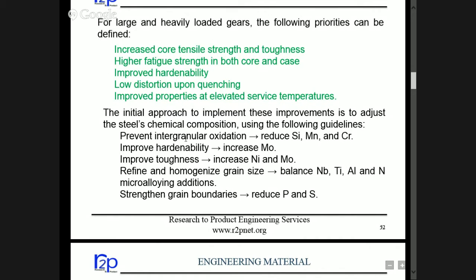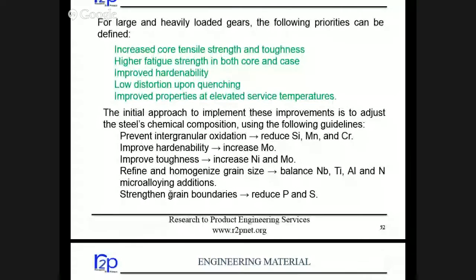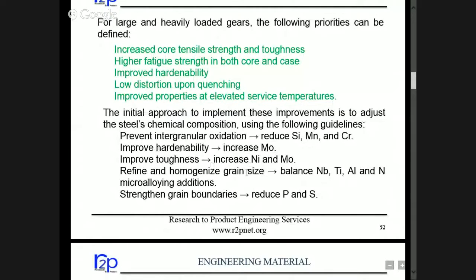Prevent intergranular oxidation. This is done by reducing silicon, manganese, and chromium. So you can say that aluminium killed or refined steel we should use, where the phosphorus, sulfur, or silicon are not there, or are at the minimum possible percentage. Improve hardenability. So addition of moly helps in that. For toughness, again nickel is the main alloying element.